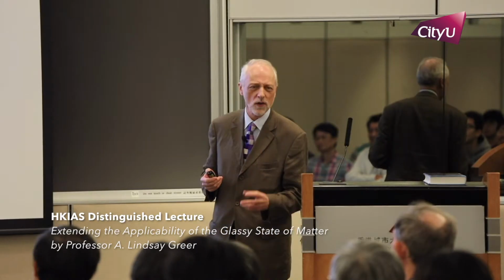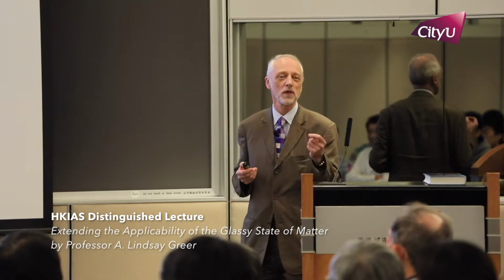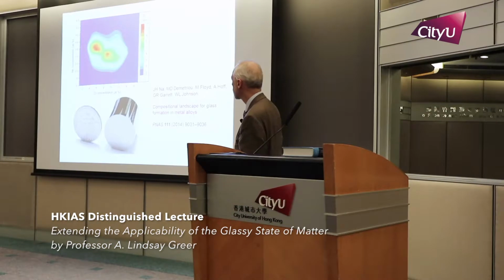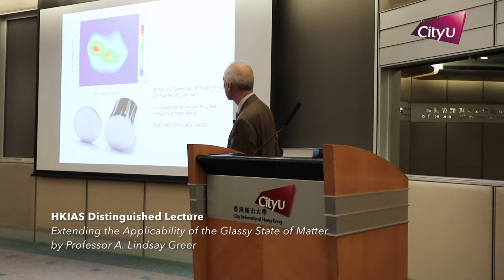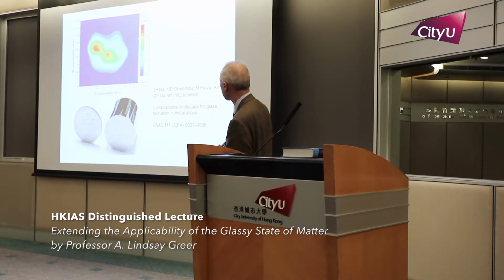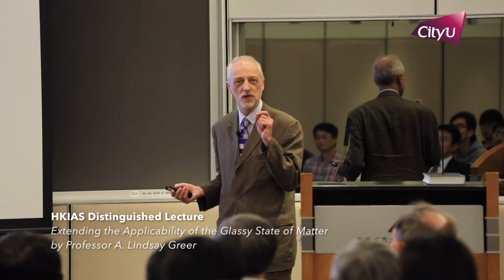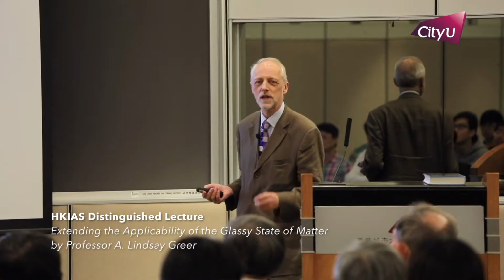This is a lower cost. There's obviously interest in getting bulk glass formation, but not with ultra expensive metals like palladium. This is really based on nickel, work of Johnson's group at Caltech, alloyed with niobium and chromium. This is a map of the diameter that you could make fully glassy, and it goes up to just over 1 centimeter. The point of showing you the map is that the critical compositions at which you get the best glass forming ability are really very tightly defined. You wouldn't necessarily have thought that. It's almost like this bulk metallic glass is a compound. It's just it happens to be a compound with a non-crystalline structure, if you like. Here it is compared to an American dime. Nice sample.